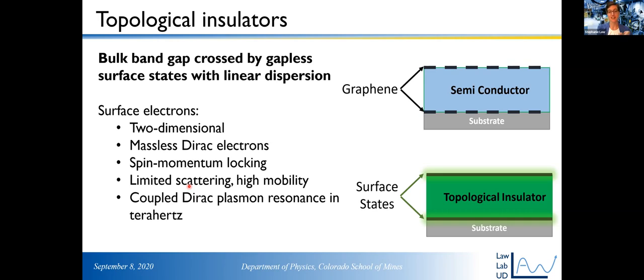This also means that an electron traveling in the plus X direction with spin in the minus Y direction can't just scatter into a different surface state with a different momentum, because it would also have to undergo a spin flip, right? So this means that electrons in the surface states traveling in the plus X direction can't just scatter into other surface states in the absence of a magnetic impurity. So that means that you should get very high mobility from these electrons.